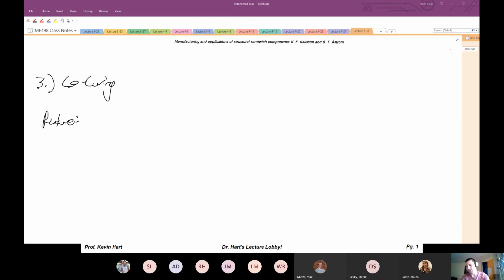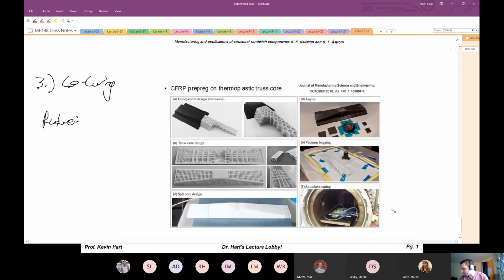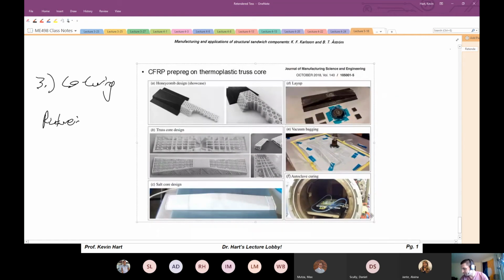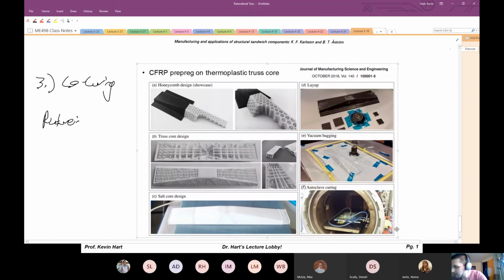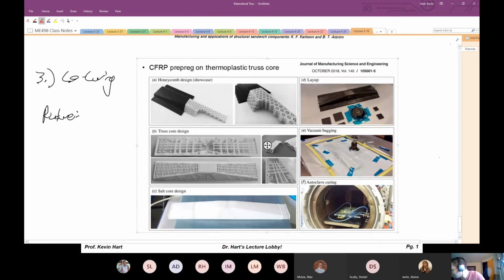And I particularly like the series of images that I found in this paper because it explains the process of co-curing very well. So here's the general idea. These people made this thermoplastic material core. I think they 3D printed this actually, which is kind of cool. This looks like polycarbonate, I think, but I'm not sure. Some thermoplastic, polycarbonate could be a possibility. And then here you see prepreg carbon fiber, which is being draped over the thermoplastic core.